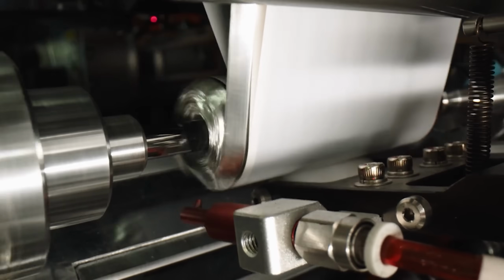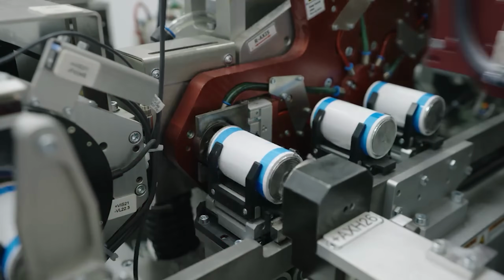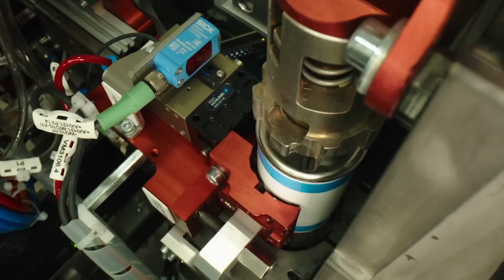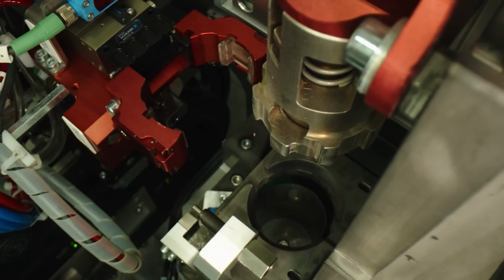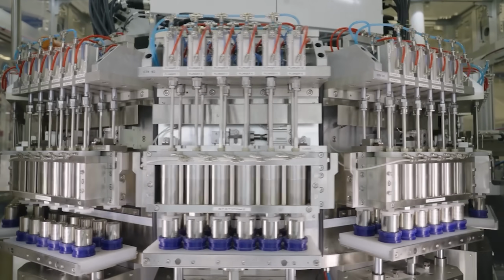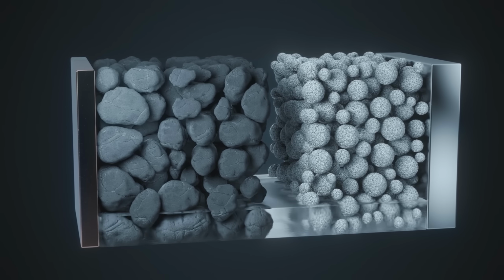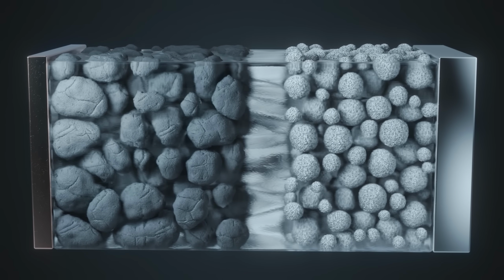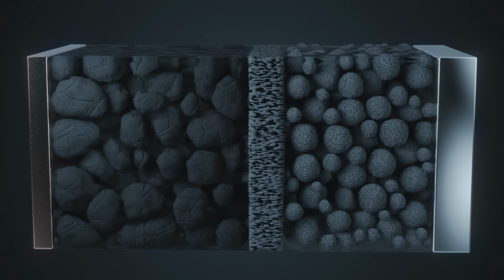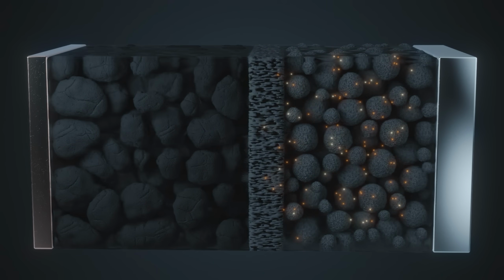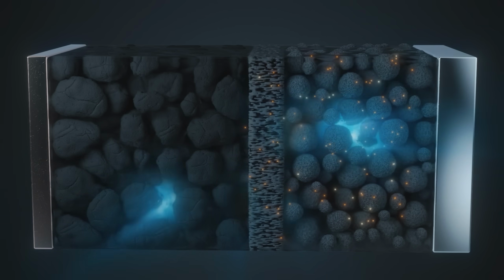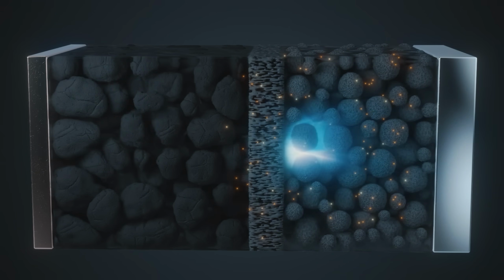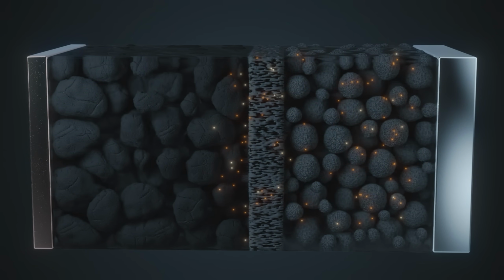After the electrode is coated, it's married with a separator and rolled into what's called a jellyroll. The jellyroll is then inserted into the battery cell, which is then filled with electrolyte. The entire jellyroll must completely absorb that electrolyte because it's what allows lithium ions to travel between the cathode and anode, which is how lithium-ion batteries store and release energy.